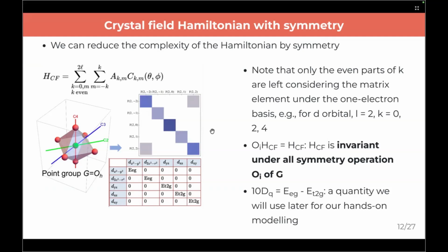So in this regard, if you use such symmetry information, it will simplify, I would say, how heavy the calculation might be, because now you can convert the matrix to a more sparse type, which will save you some time when you try to solve the eigenvalue problem, for example. And here, this matrix is written in the spherical harmonics basis.